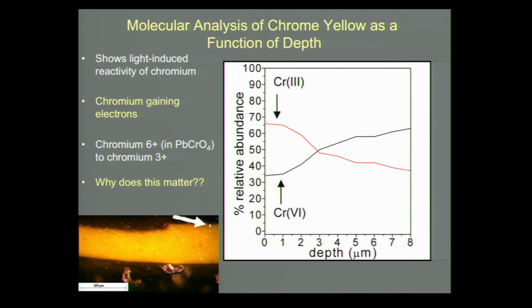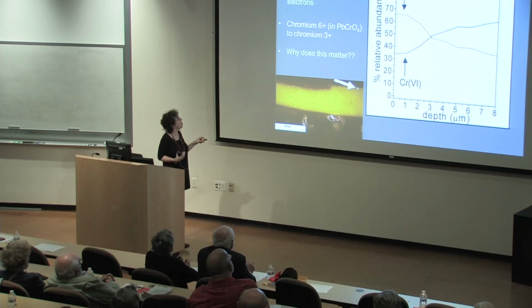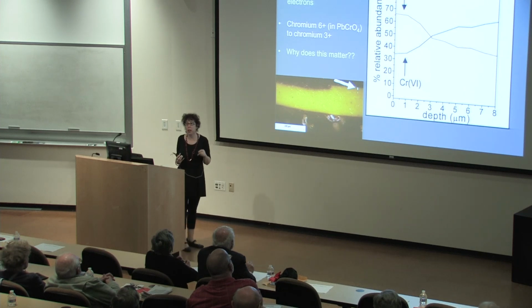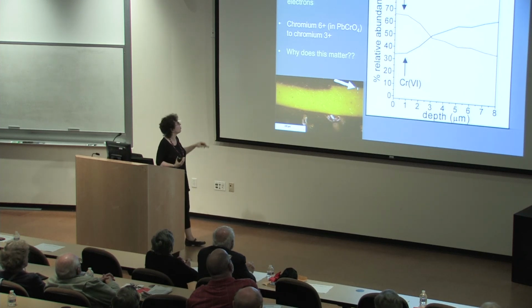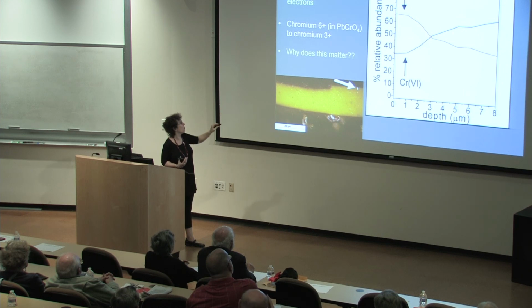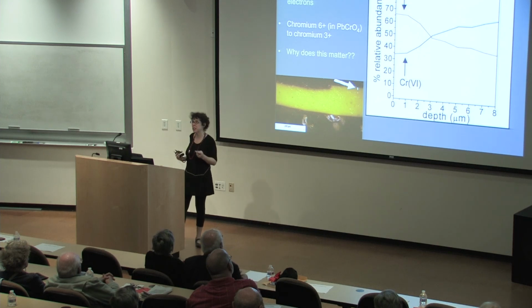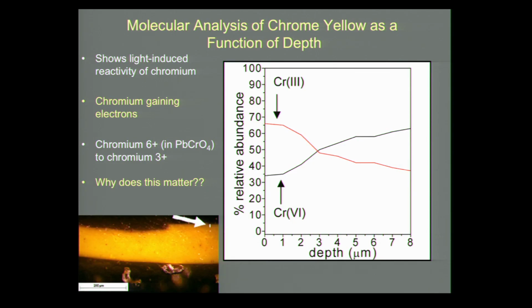So here's what the molecular analysis of the paint layer looks like as a function of depth. So we're looking at depth into the painting in this direction, and what we see happening is the light-induced reactivity of the chromium in the chrome yellow. And so the chromium is actually gaining electrons when it's exposed to light. So inside the chrome yellow pigment, which is a lead chromate, we have chromium 6+. So in the center of the paint layer here, we have chromium 6+, but on the surface, we have chromium 3+. So what we call the oxidation state has changed. So why does it matter that the oxidation state has changed on the surface?